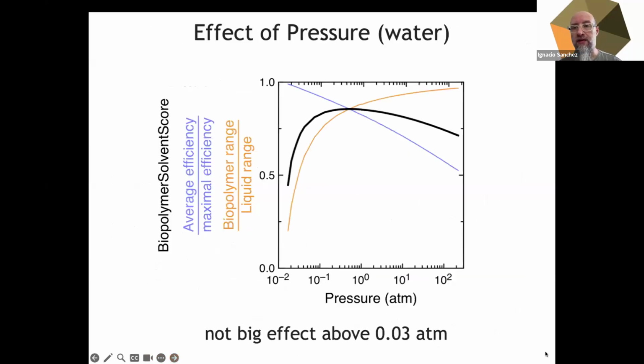You may argue that these properties of solvents, the characteristic temperatures for freezing, boiling, and the dynamic transition, would vary as a function of pressure. That may be so. The question is how much. We used water to consider this and calculated the biopolymer solvent score of water, that's the black line, in the range of pressures where we find water in our solar system.